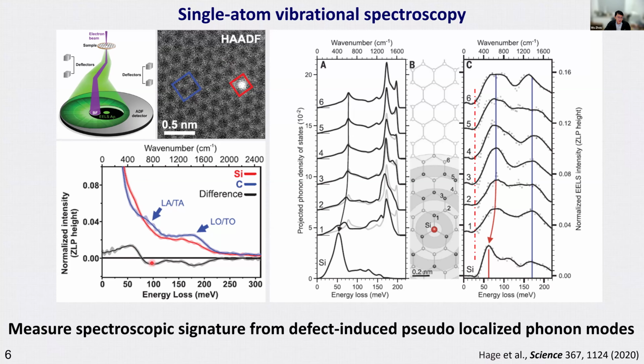And this very subtle difference can be reproduced by the calculated phonon density of states projected onto different atoms. So this is the very first demonstration that vibrational EELS could achieve single atom sensitivity. But here, from their calculation, they actually see that apart from this silicon atom, which shows a very different signal from the graphene lattice, the carbon lattice around the defect also shows energy shift. But in the experimental data, it's very difficult to see.